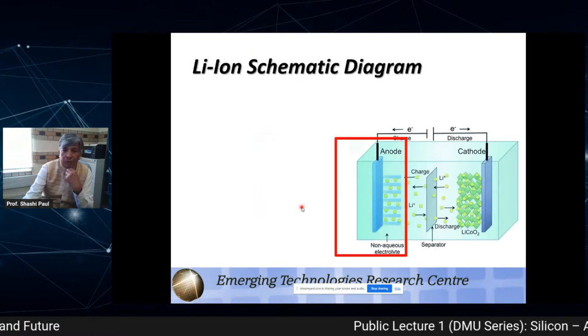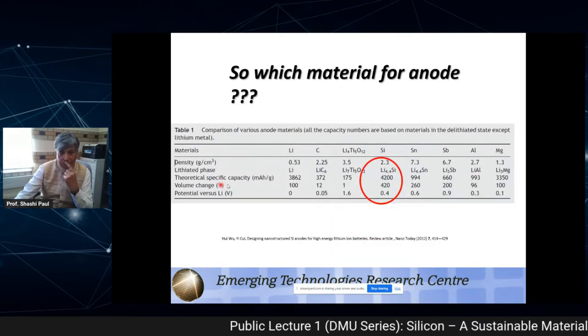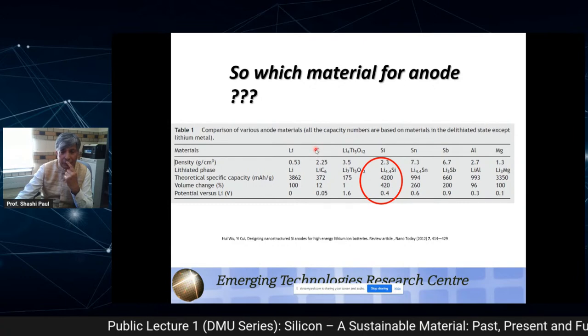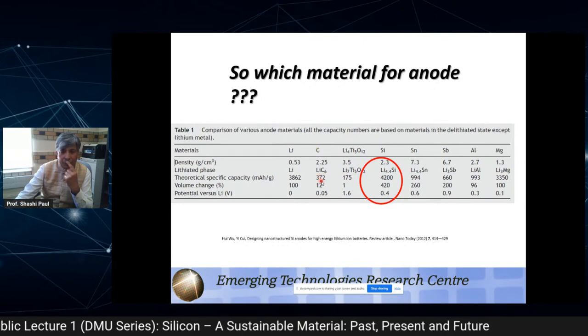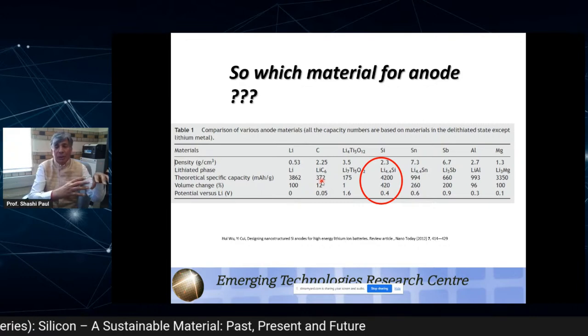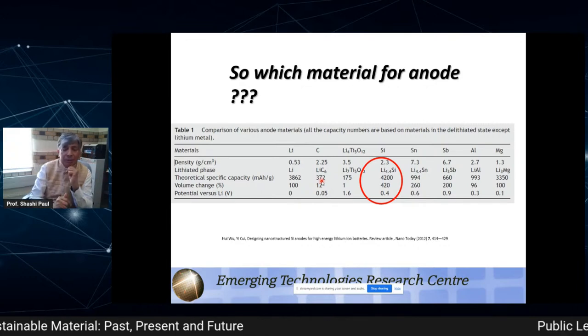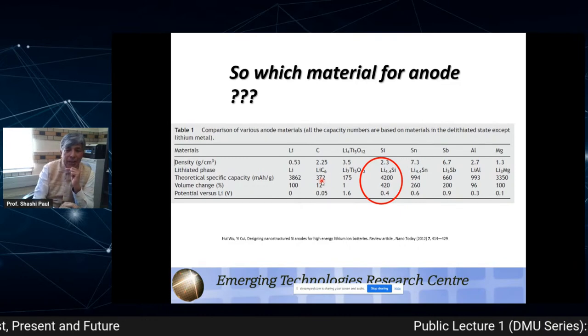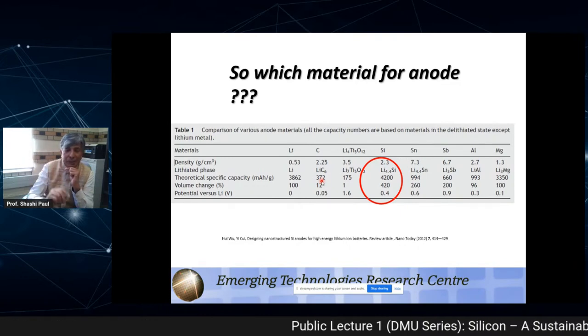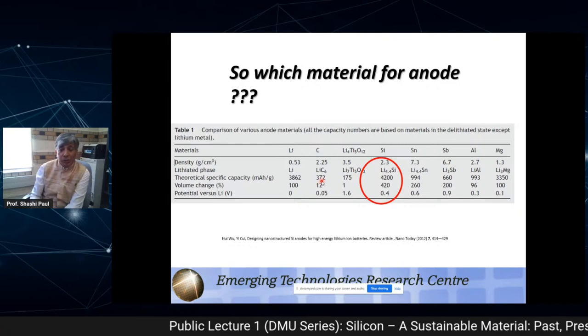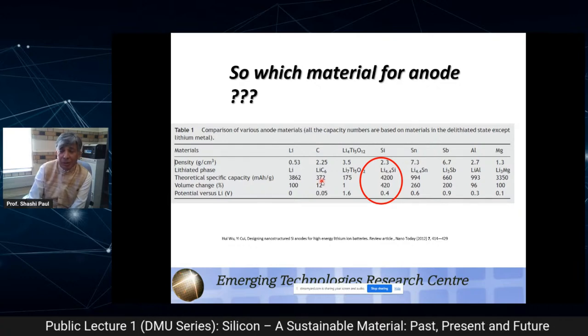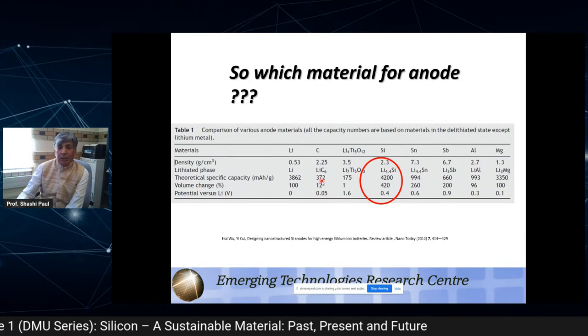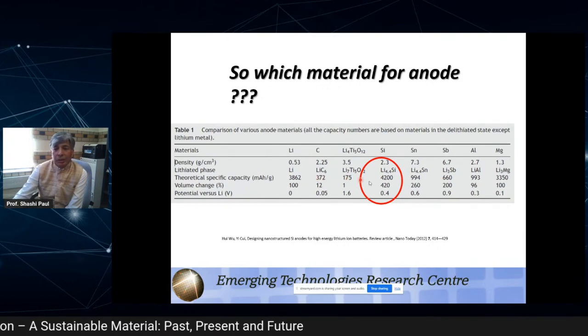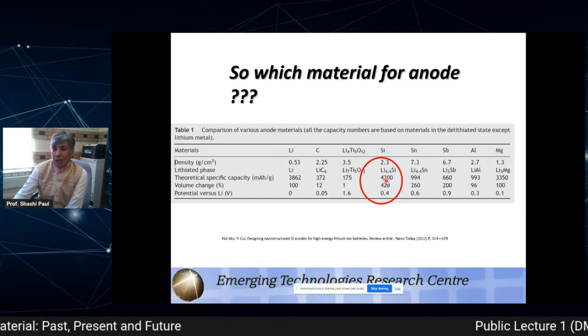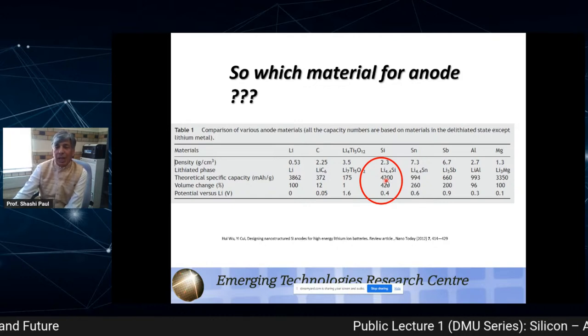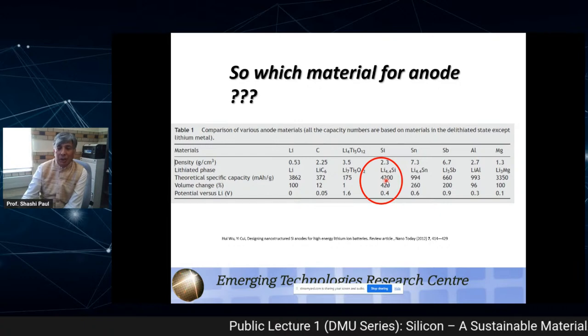So now if we talk about carbon, which is currently used, it can take around 372 of those lithium charges per gram. Okay, not necessarily in that way, but let's take it that way. So it can take a certain unit of charge, which is 370, in that porosity. But silicon, contrary to carbon, takes 10 times more charge, around 4,000 charges. It means that the battery will last longer. You can store more energy.